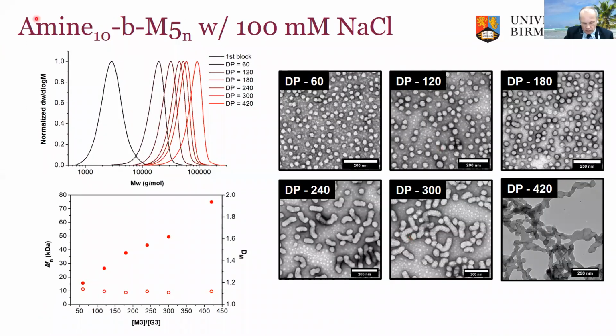So just doing the same polymerization I showed you a couple of slides ago where we hadn't seen a change in morphology, now you can see quite clearly, when we repeat this in a salty solution which screens charges, we're seeing very similar fusion events and the formation of these tubosomes as we saw for the PEG-based system.